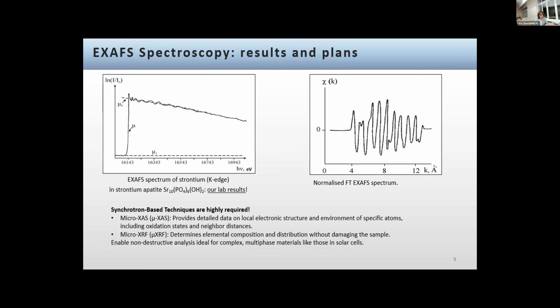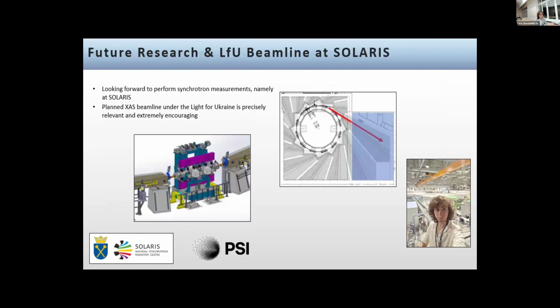the X-ray fluorescence measurements would be especially relevant too, because as I said, when we are studying the degradation processes, the migration of ions is specifically important in the interface region. So we can trace the state of decomposition of the perovskite by tracing the distribution of certain concentrations of atoms in real space with it. Right, and with this I slowly come to the conclusion, which is, of course, talking about synchrotron experiments. Primarily, we are interested in the collaboration with Solaris, and it already has some beamlines that may allow to perform such experiments, but